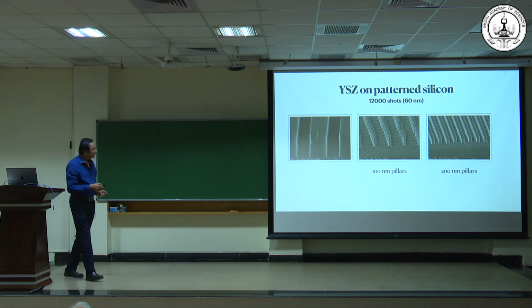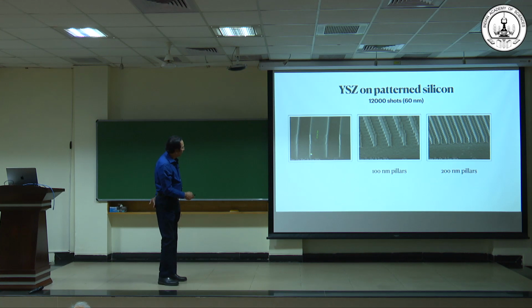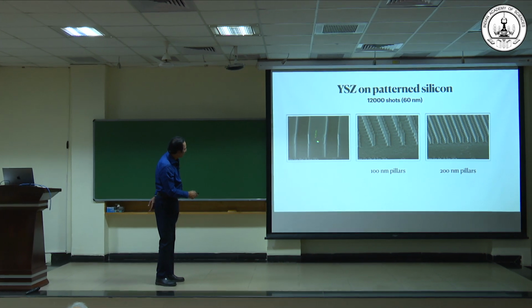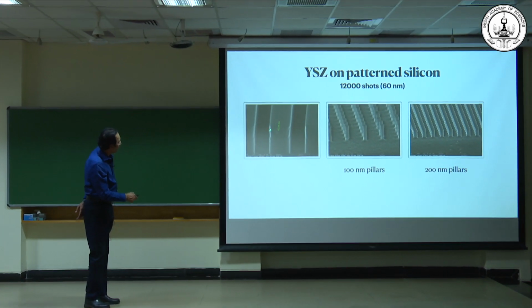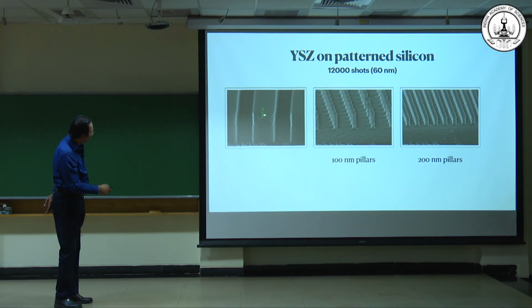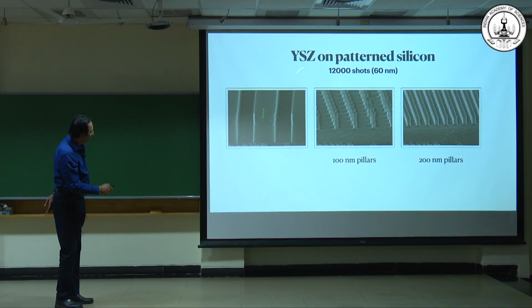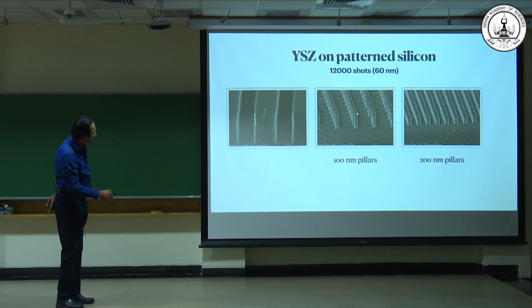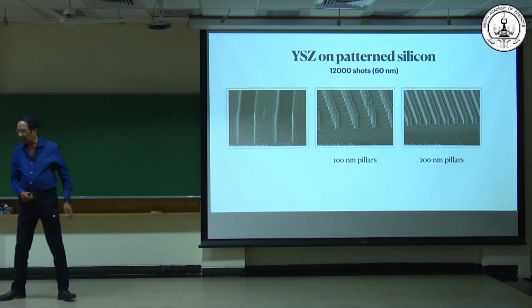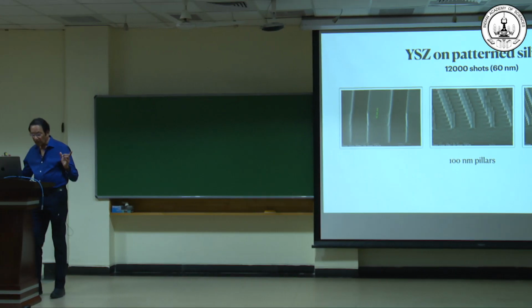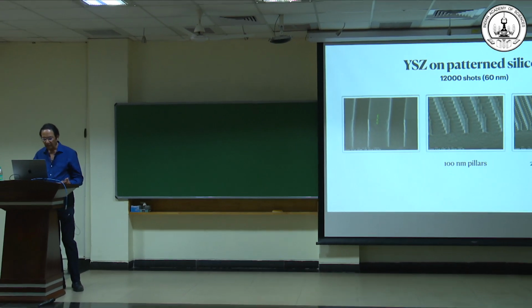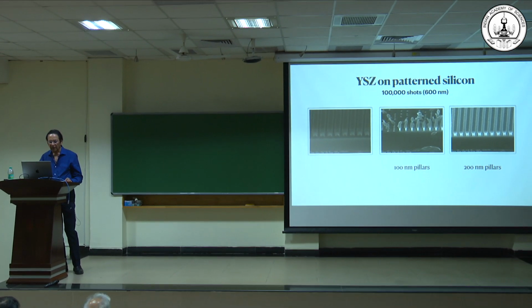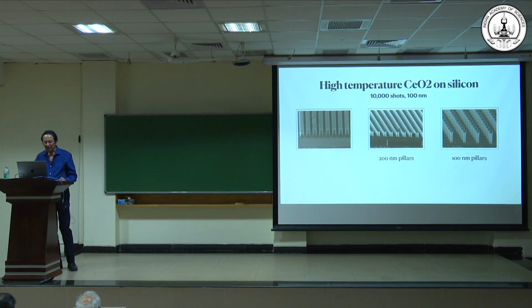So you see here, this is a silicon pattern, a wall about this tall, right? And this is an oxide, yttrium-stabilized zirconia, grown on top of the silicon. Similarly, here's a little cap of YSZ on top of this little pillar of silicon, and there are like 200 nanometer pillars, and you can see they're all on the top of the thing. You create these little discs of YSZ, and these are single crystal films. And so we can do that for things like cerium oxide.